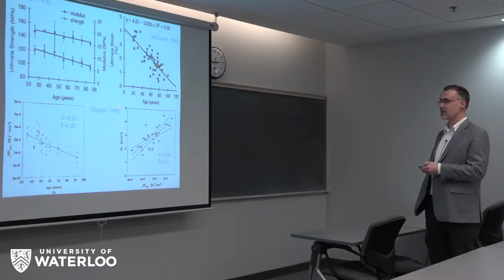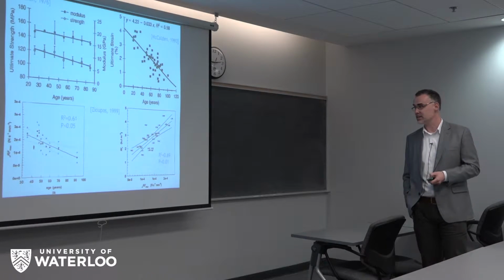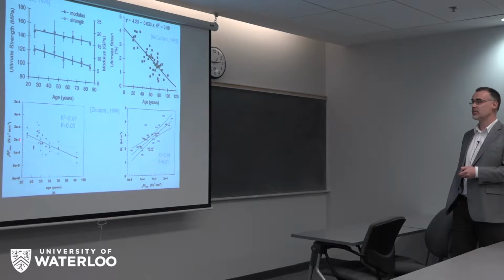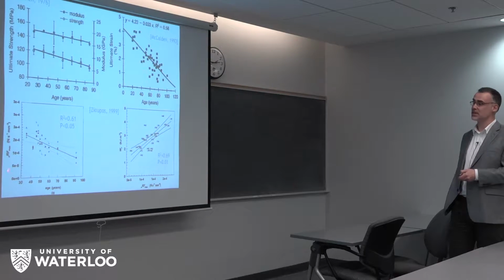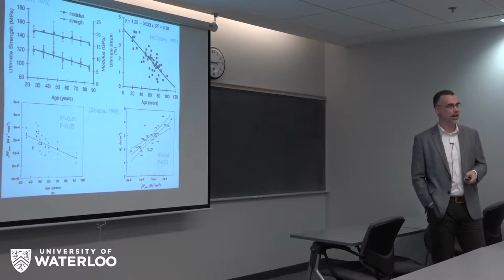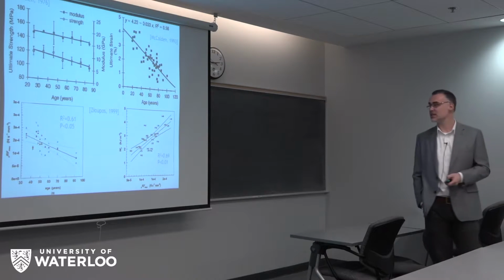And it turns out that Peter Zioupos from England, quite a while ago now, measured connectivity using a thermomechanical technique, which I'll get into later. And he showed that the connectivity of the collagen decreases with age. And so that's a lot like what happens with irradiation sterilization.